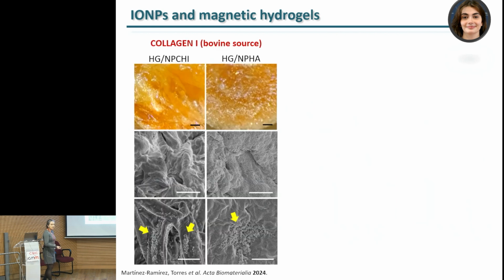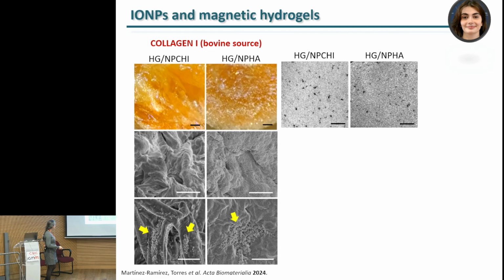And then the next step was, as I mentioned before, we like 3D things because we want to replace a 3D element. So she incorporated that into collagen hydrogels. You see here how collagen naturally is whitish because of the dispersion of the light by the collagen fibers. But you see here how it turns more brownish because of the loading of the iron oxide nanoparticles. And indeed, in some details, you see here how we could find some groups of iron oxide nanoparticles in the borders. But naturally, they were well distributed in the matrix.